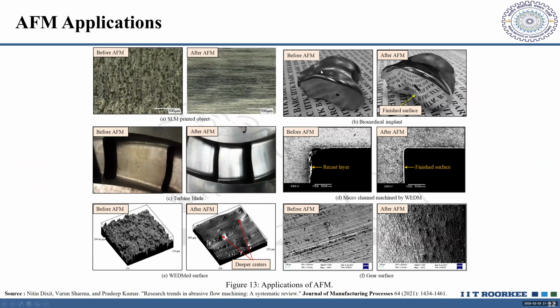So if you see this particular thing, to get these kind of shiny surfaces, to get these kind of finishes from matte to glossy, you have to not only optimize your process parameters, but at the same time, you have to selectively choose the type of the abrasive, the size of the abrasive, and the concentration of that particular abrasive in the abrasive media. So these sharp edges, which are there for a Pelton wheel or the turbine blades, may have certain kinds of burrs. All this deburring, all this micro level of material removal is possible only and only by this AFM process. There is no other alternative as of now, even in the existing industry, to do the finishing of those small holes which are there in the turbine blade. Even the DRDO's labs are using AFM for that particular application.